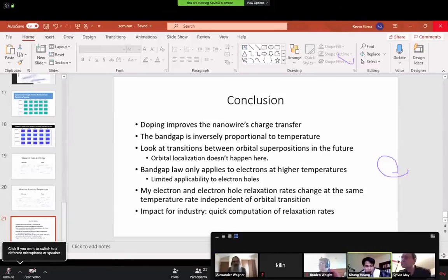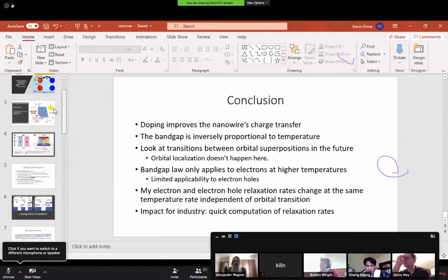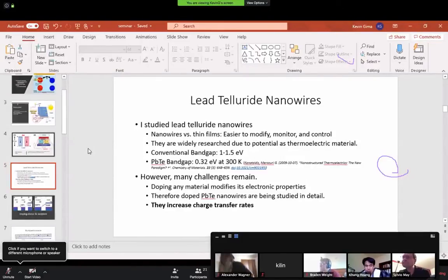Right. So my question is about the band gap. Are your calculations sensitive to the value of the band gap? I raise this issue because certainly the band gap value obtained in your calculation is wrong because you did not include spin-orbit interaction.